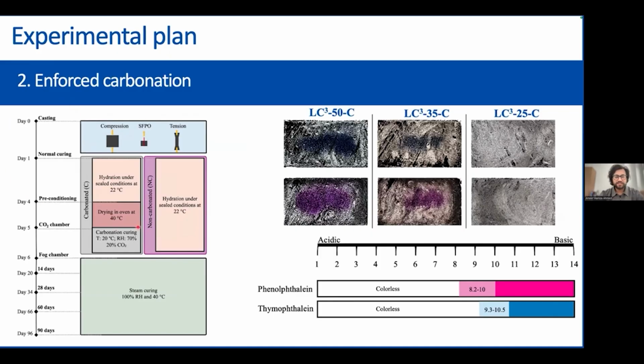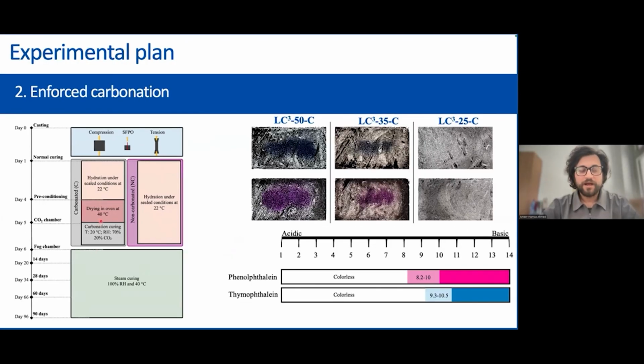So here is the scheme of how we cured the sample. At first, we cast the samples for compression, single fiber pullout, and tension test. And after 1 day of in-mold curing and 4 days of normal curing according to these conditions, we dried the samples for 1 day at 40 degrees centigrade, for the set of samples which we wanted to carbonate. The other set was kept for normal hydration in the standard lab curing chamber. This drying was to open the pore structure so CO2 can penetrate deeper. And after the 1 day, we carbonated the samples according to these conditions for 1 additional